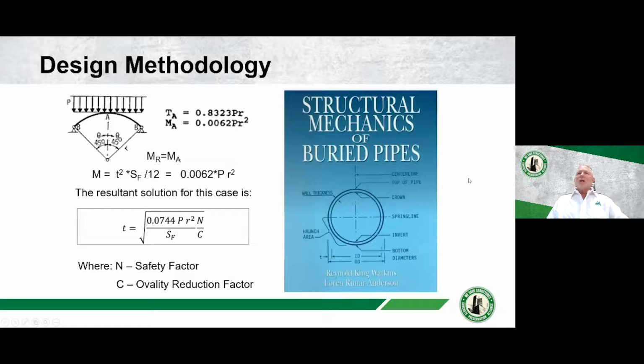For the applied moment, what we did was went to the book, The Structural Mechanics of a Buried Pipe, which shows a setup that I think is very representative of what we have with a culvert lining system. It's called an arch beam design. So what we have is we are using an arch of a quarter of the pipe with pin connections on either end and a uniform applied load. For that, we get an applied load moment of 0.0062 times P, which is the load, times the radius of your lining squared.